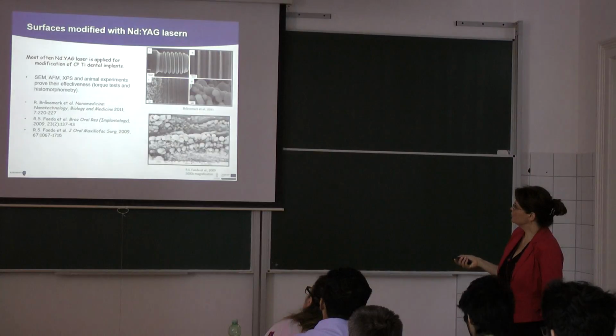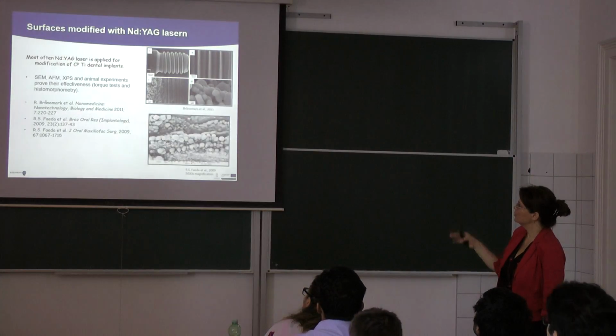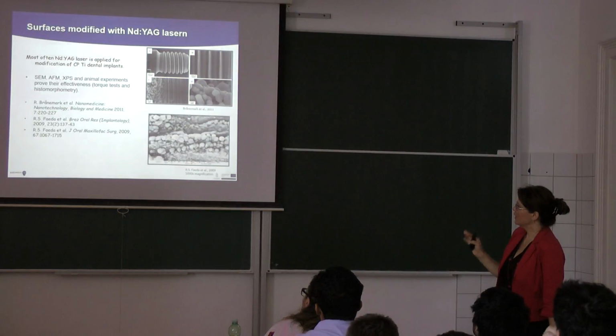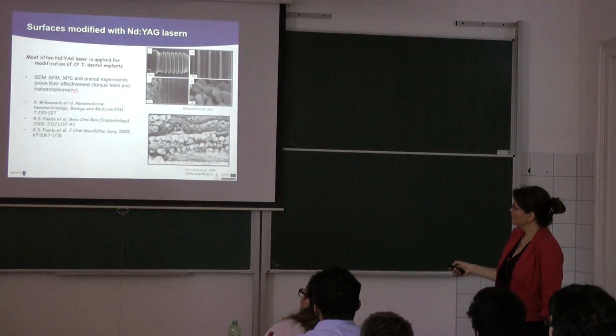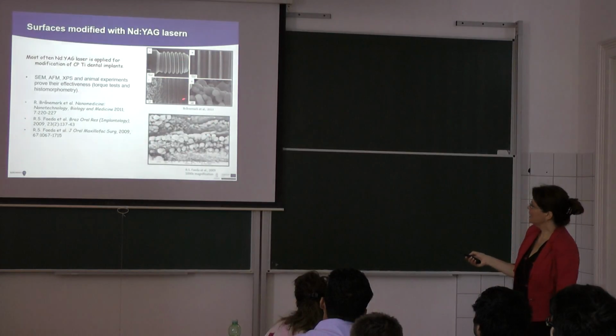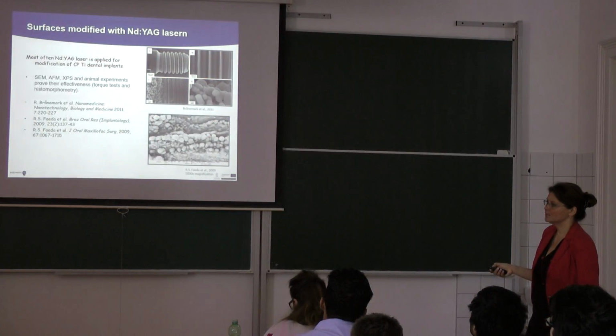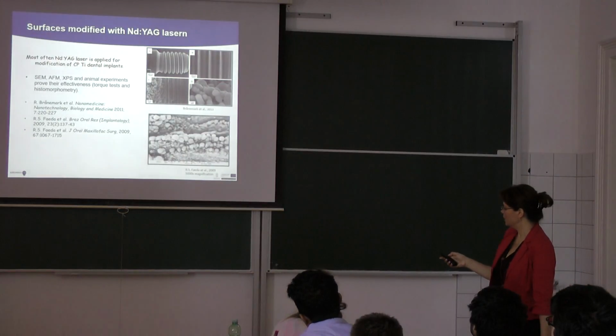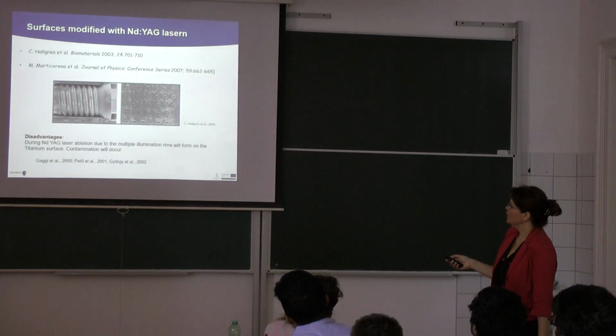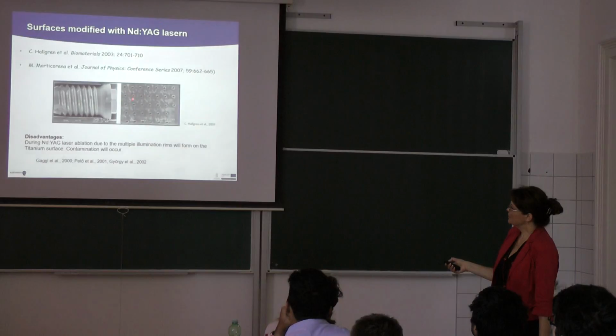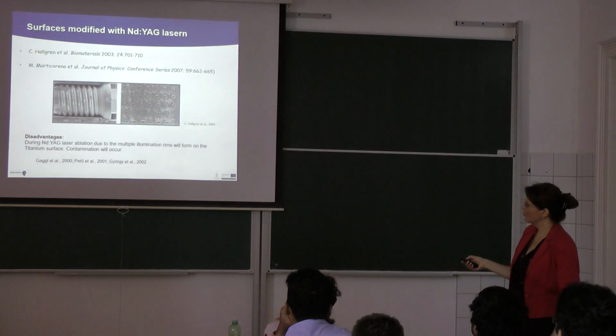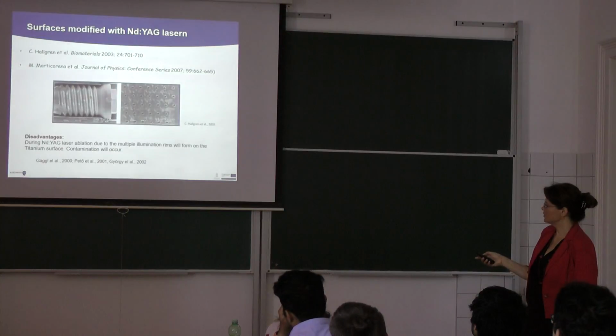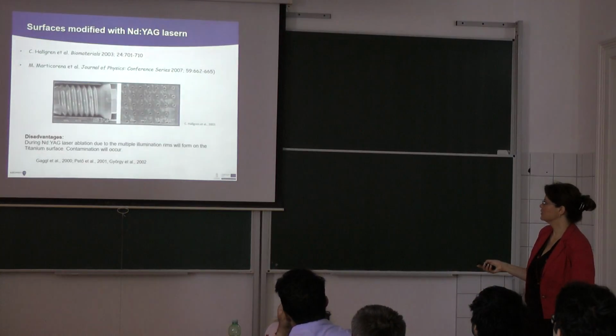If I turn back a little bit now to the lasers, I am not saying that they are not good or not available. This is the son of Professor Robert Grönemark, who was doing very nice surface modification of dental implants using a neodymium laser. It is a very sophisticated technique, which I cannot describe, but they had already made animal testing showing that it is working nicely. But typically what we can see is that they are making these holes and the rims are not good, which we could see in our research and is also proved by other researchers.